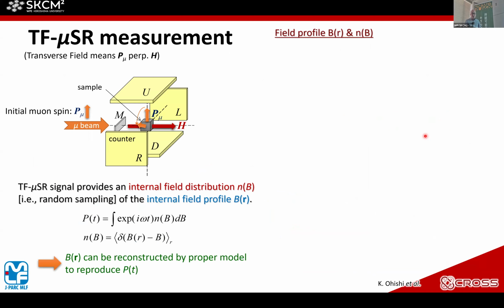When we use the transverse field μSR measurement technique, with the magnetic field applied perpendicular to the initial muon spin like this, this signal provides an internal field distribution, because muons stop in the sample at several points. It means that muons do random sampling of the internal field, picking up the internal field randomly. After that, we can extract the internal field profile in real space using a magnetic model.